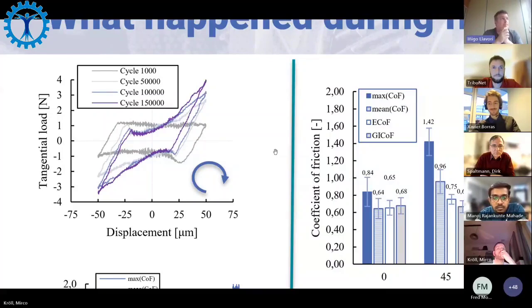And the fourth one is the geometric independent coefficient of friction, which is kind of difficult to say how they calculate it, but essentially you take into account the compliance of the contact system, and then you calculate exactly the midpoint of the test. And at that point, the vectors of the friction force and what the sensor measures are aligned. So in that sense, you are calculating exactly the friction coefficient, because both vectors are aligned. The problem I encounter with that method is that it is very sensitive to the noise, so you have to be very careful. But essentially, those are the 4 methods I know.